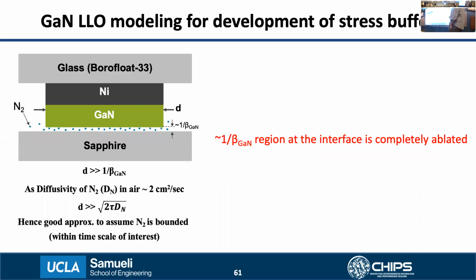In this slide, slide 61, you can see how that simplification was done. Again, I've replicated the cross section here. We assume that all the GaN within the penetration depth of the light is completely decomposed into liquid gallium and nitrogen gas. We can make two observations here. One is that the diameter of the GaN thin film is much greater compared to the region of the GaN that has actually been ablated. And also, at this particular temperature and within the timescales of interest, which is a few pulse widths in the tens of nanosecond range, the diffusion length of the nitrogen gas is much smaller compared to the diameter of the GaN thin film. So under these observations, we can approximate that within a few tens of nanoseconds, the nitrogen gas within this ablated region can be assumed to be trapped at this region.